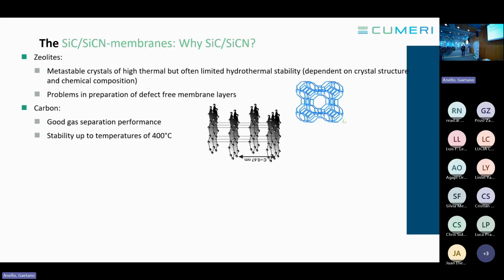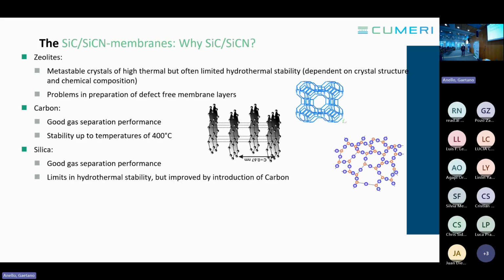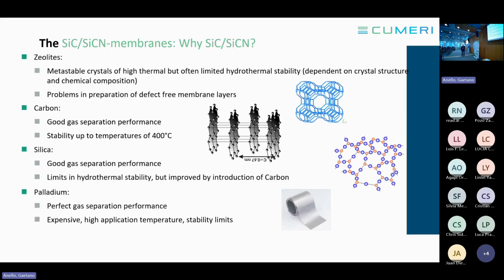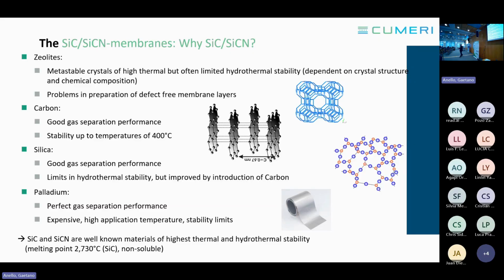Carbon has very good separation performance, but the stability is limited to approximately 400 degrees C. Silica, we all know, has limits in hydrothermal stability, but it can be improved by introduction of carbon. There's palladium, which would be the perfect membrane for hydrogen separation, but we know it's expensive, needs a high application temperature, and there are also certain stability limits. However, silicon carbide and silicon carbide nitride are well known in the ceramic industry to be very stable, hydrothermally as well as thermally. The melting point of silicon carbide, to give an example, is more than 2,700 degrees C, and it's not soluble in any acid.